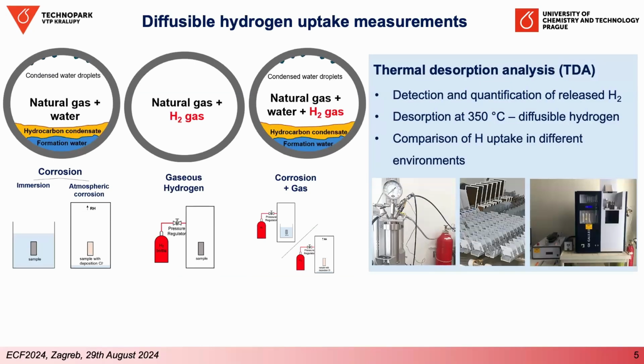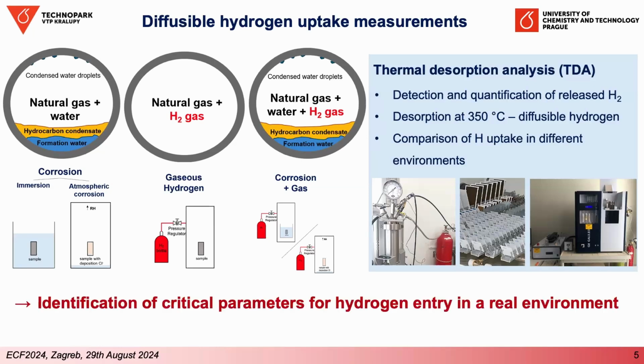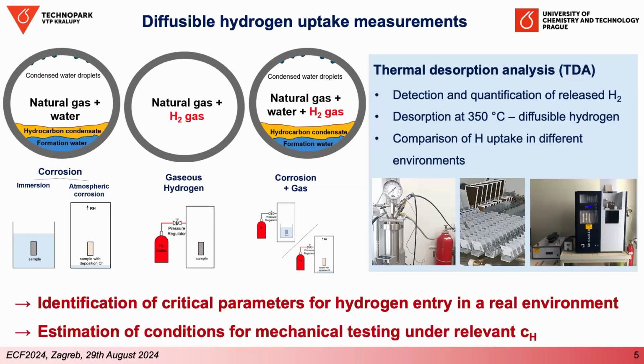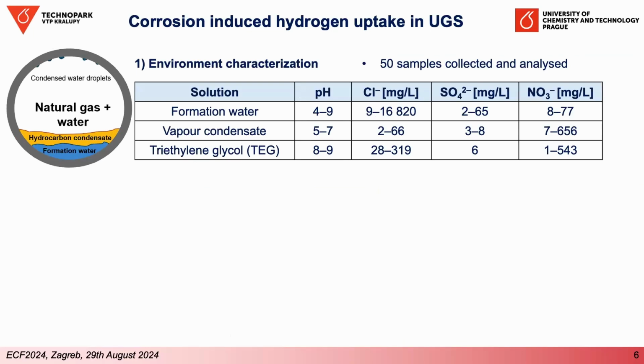We are modeling these situations with corrosion exposures and with autoclave. Then we are quantifying hydrogen with TDA and trying to identify critical parameters for hydrogen entry. And of course, then we are trying to connect it with the mechanical testing, but we also have, as many researchers, the electrochemical in situ testing. So we are trying to do our best to really reach some relevant concentration and some trustable data for this practical tool. So first of all, it was the mapping step to really understand what is happening there,